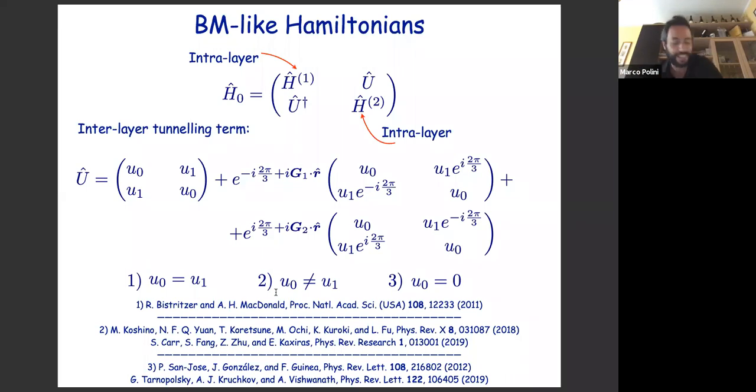But essentially the main point I want to convey is that by carrying out a detailed experimental study of the dependence of the optical conductivity and the collective excitations with respect to the ratio U0 over U1, you are able to extract experimentally, for that particular sample, the actual value of the parameter U0 once you fix the other one. It may vary from sample to sample. So we believe that you gain very useful information by carrying out these optical studies.